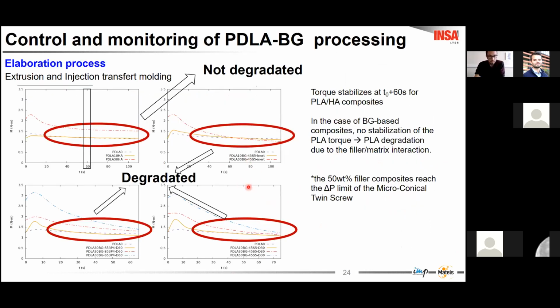As previously done in part 1, we monitor the torque of the twin screw. Here we can see the torque as a function of time, and we have seen that the torque decreases over time, showing a degradation.